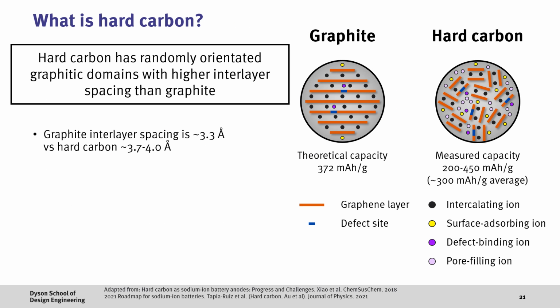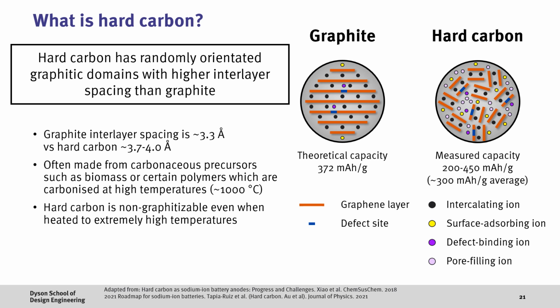Now, given that hard carbon is the most likely first anode material for commercially viable sodium-ion batteries, it's worth spending a bit more time discussing them. Here, hard carbon has randomly orientated graphitic domains with a higher interlayer spacing than graphite. Hard carbon can be made from different carbonaceous precursors such as biomass and certain polymers through a heat treatment process, which results in non-graphitizable structures even at high temperatures. These materials often have a high surface area and porosity with lots of defects, which results in multiple different ways sodium ions can be stored in their structure. However, because of this high porosity, the density of hard carbon is generally low, resulting in poor volumetric specific capacity.